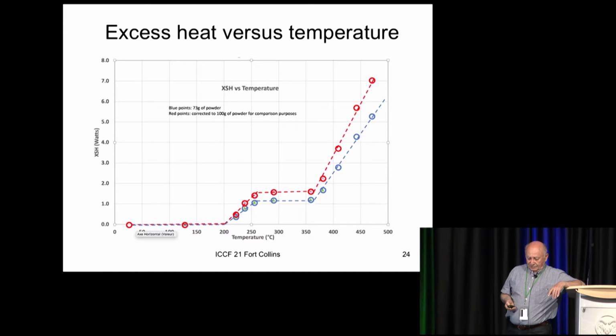Here's the new curve. It's more interesting, but there is a plateau. I don't know if the plateau has any meaning. It could be in the error bars. I don't know. But you see that I got more than 5 watts, and you normalize it to 100 grams, you get 7 watts. And it seems that now it's going up with temperature, which is very, very exciting for me, because I plan to go to higher temperatures. That means that there is a lot of hope in this technology.